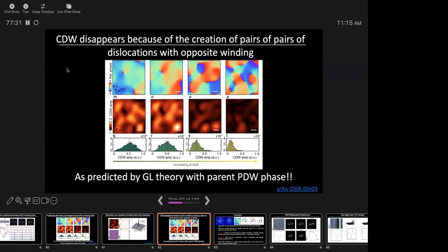You don't see the vortices themselves? No, we don't. It's a difficult experiment. One of the reasons is the density of states is so high at the Fermi energy. The way we usually see vortices is through the bound states, so that there's a contrast. There's a bound state inside the gap, and there's a contrast. Here, it's just really hard to see vortices because of this gigantic density of states, and so the contrast would be tiny.